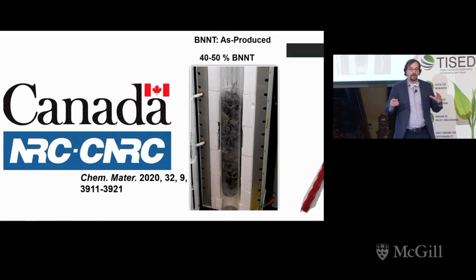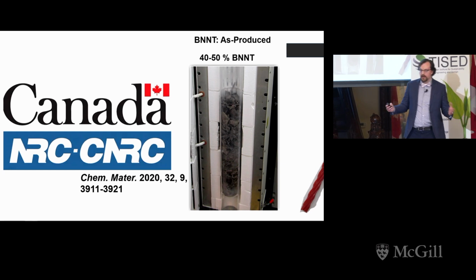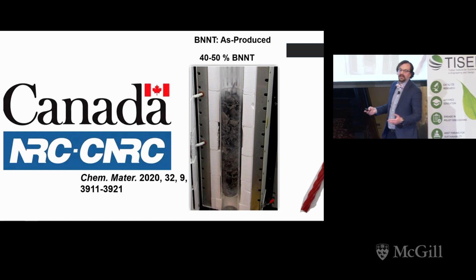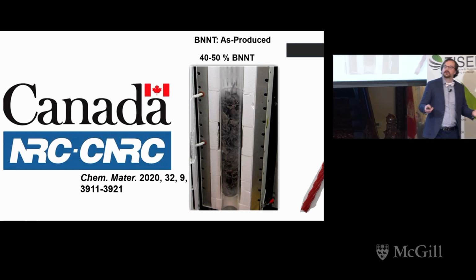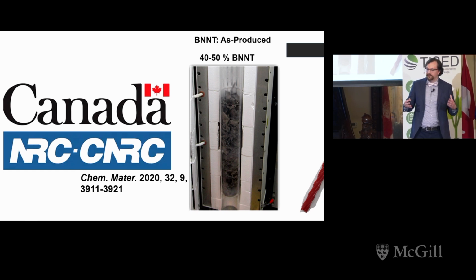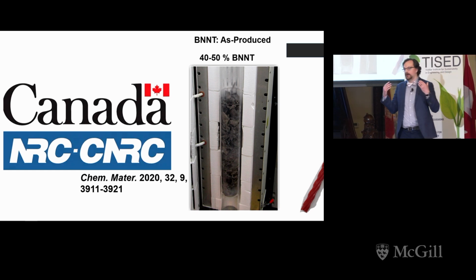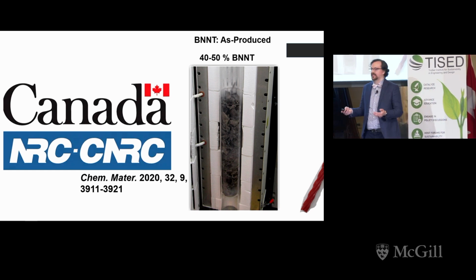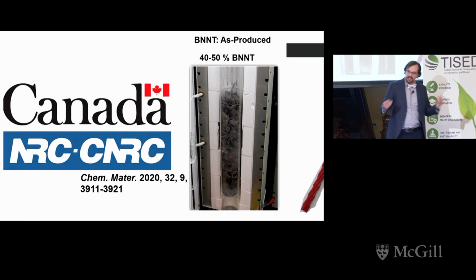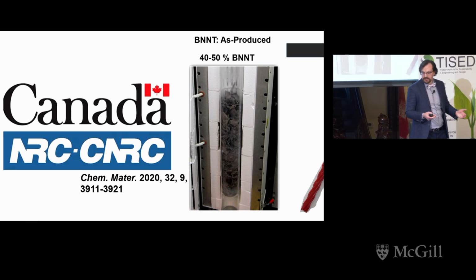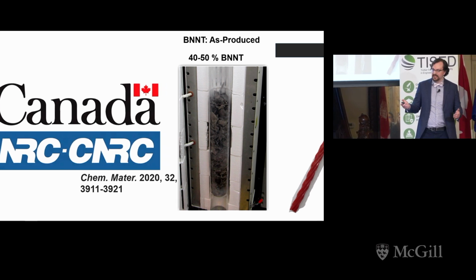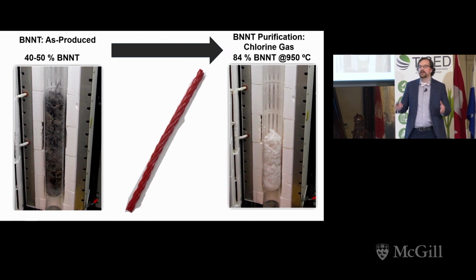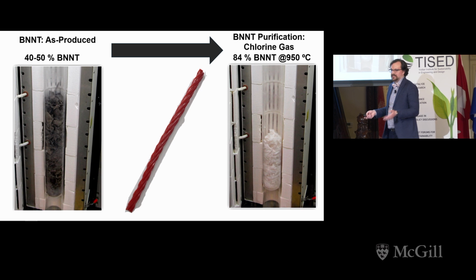Now, why boron nitride nanotubes? Well, I spent 4 years working at the Canada National Research Council with my research group on boron nitride nanotube purification. There, we were able to take our purity of boron nitride nanotubes from 40 to 50%, all the way to 84%, using a chlorine gas treatment at 950 Celsius.